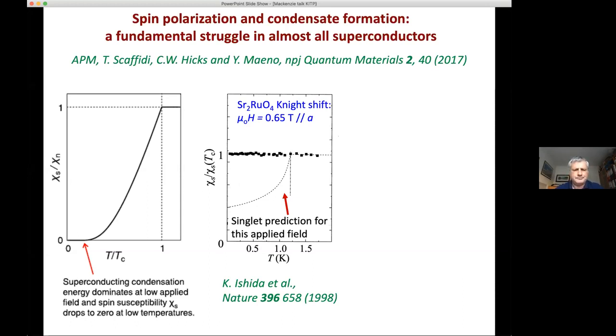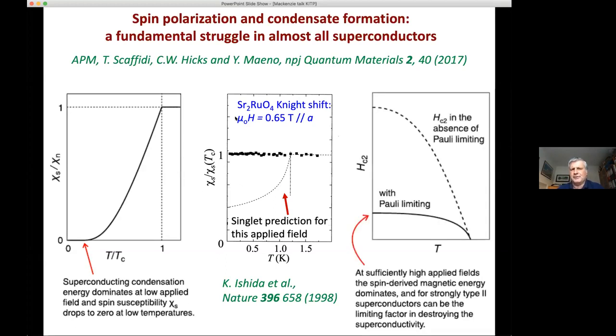That's why it was so influential that for about 20 years, we believed the spin susceptibility measured by the NMR Knight shift stayed completely temperature-independent as you went through TC. That is not only contrary to a singlet interpretation — it's very restrictive on the kind of order parameters possible within a triplet interpretation, so it was a result containing tremendous interpretive power. As the years went by, there were many reasons for getting worried. The most direct one was that there are two limits to this struggle between spin polarization and condensate formation. At high enough fields, the field wins out, giving critical field behavior known as Pauli limiting. The big problem was that strontium ruthenate didn't show signs of the competition in the superconducting state at low fields, but it did show signs of the competition in the Pauli limiting.